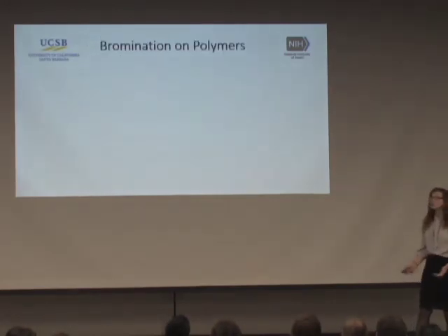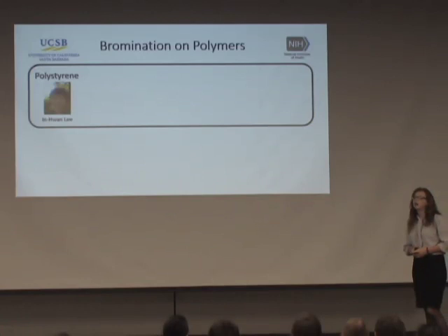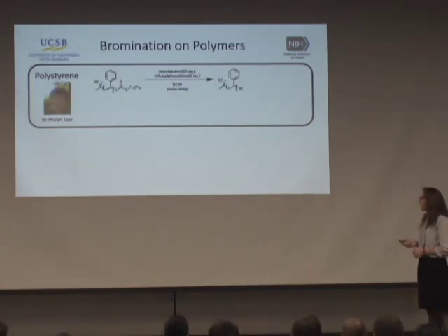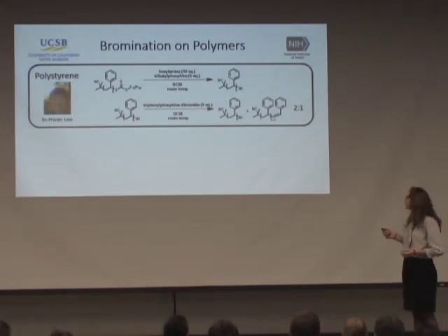And we moved on to actually doing it on our polymer systems. The first system is polystyrene. This work was done by Ewan Lee in the Hawker Materials Research Group. He first started by taking the RAFT chain end, converting it to a thiol, and then converting that thiol to a bromine. He did see bromination, however, he also saw an undesired product, the elimination product, in which you get a double bond here. We are aiming for full conversion because these two products can be hard to purify from each other. So this system needs more optimization.